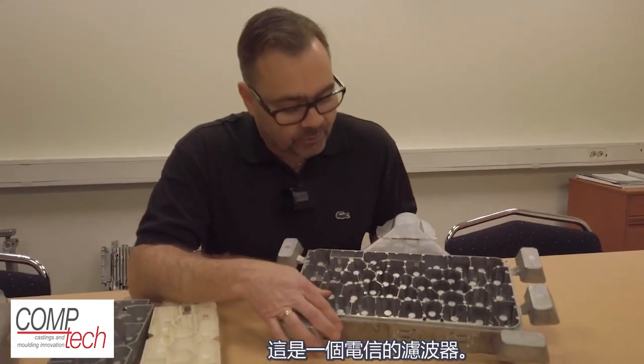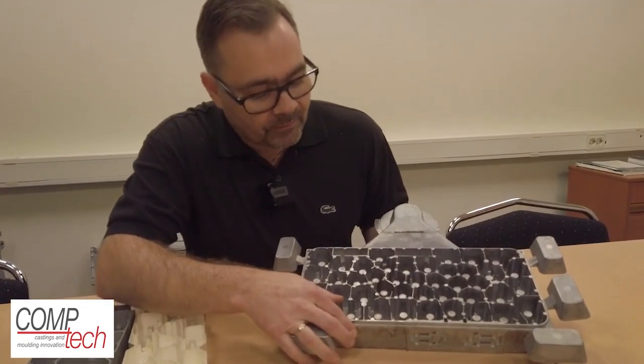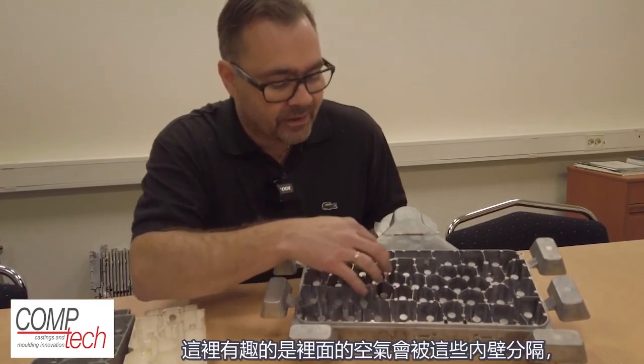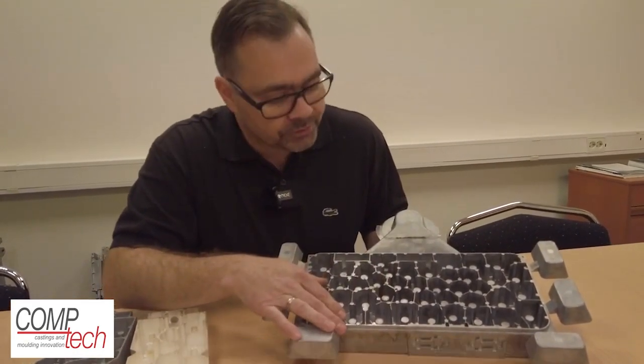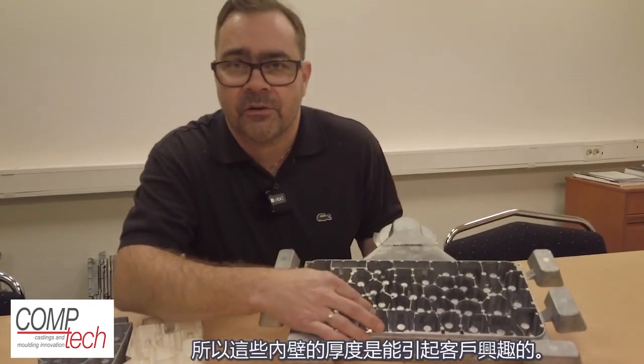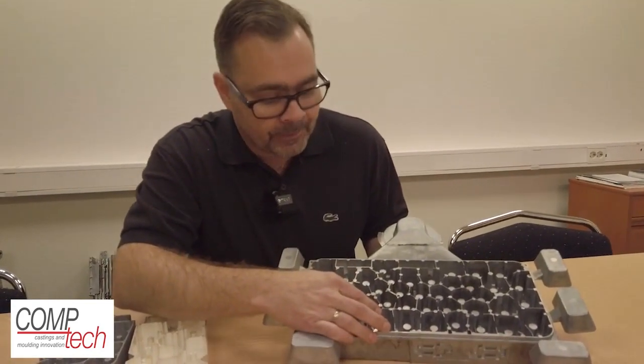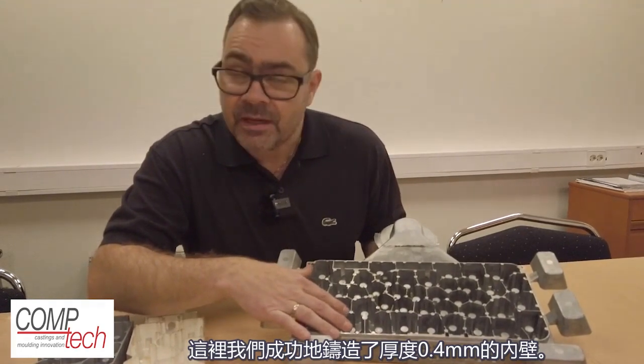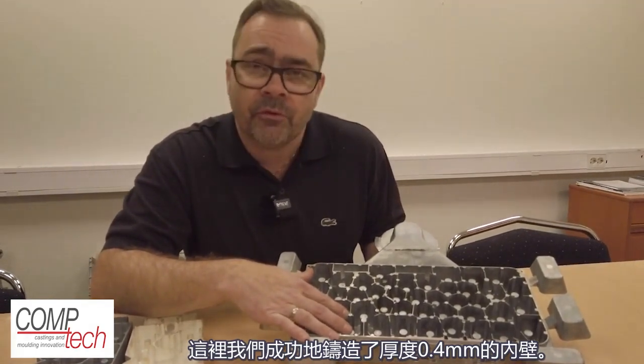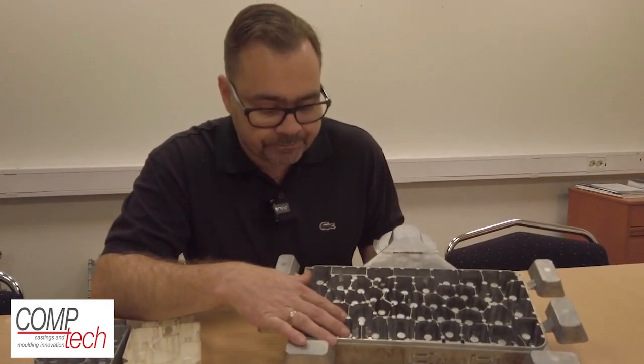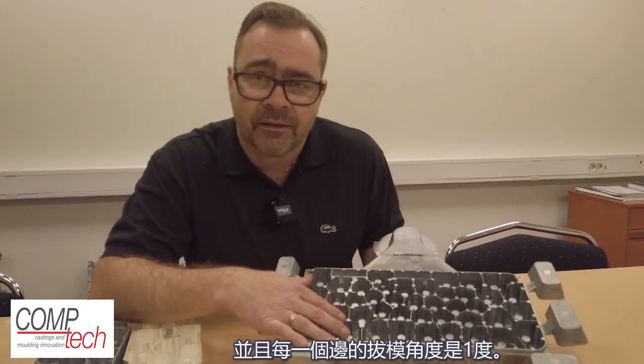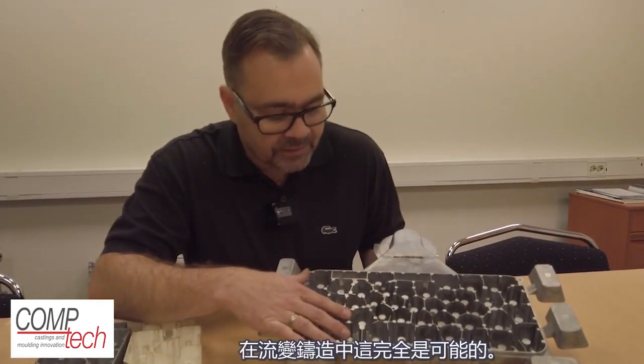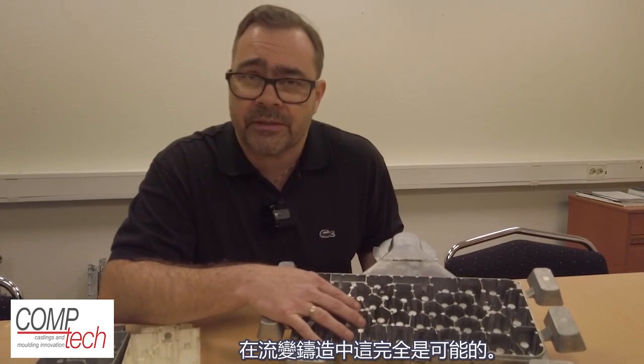This is a filter for telecom. And what's interesting here is the air that can be divided by the walls. So the wall thicknesses are of interest for the customer. Here we have succeeded to cast the walls with 0.4 millimeter wall thickness with 1 degree draft angle per side. This is fully possible with Rheocasting.